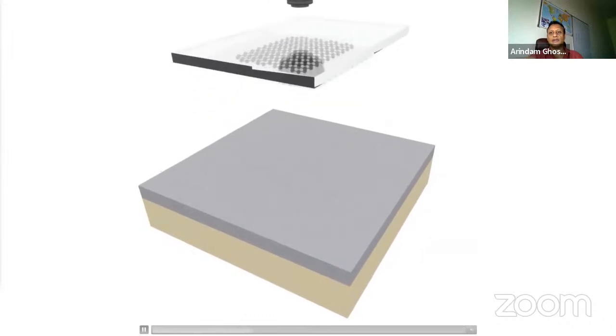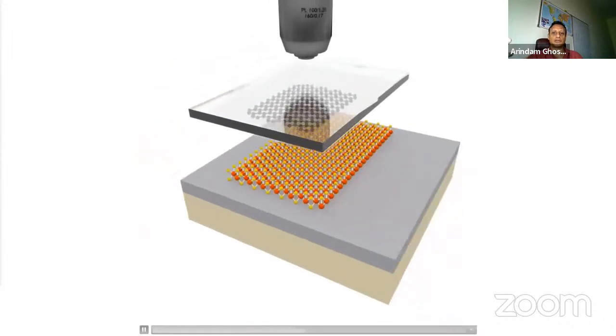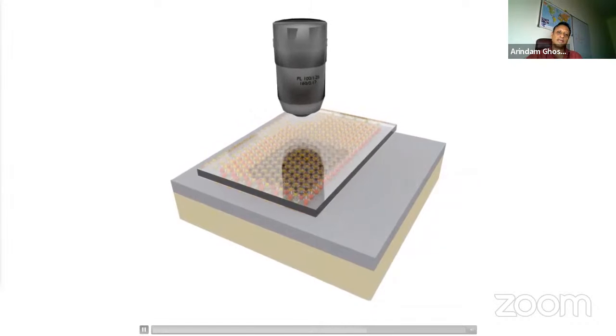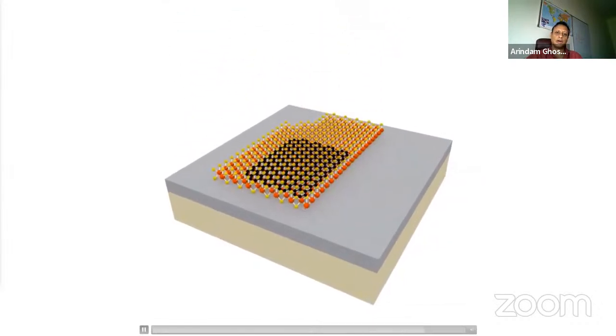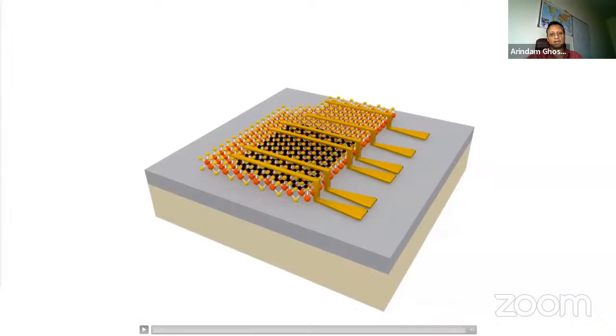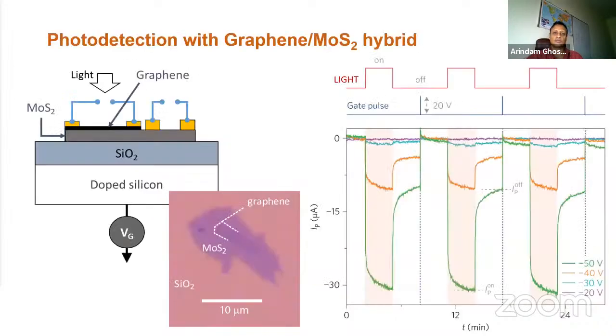That led to a new kind of optoelectronic transistor. What we did is we put the graphene on molybdenum disulfide and measured electrical conduction, something similar to this. What you see is something very interesting. Whenever you switch the light on this layer, the current through graphene, which is sitting on molybdenum disulfide, jumps dramatically by a very large number. And you can go on in cycles, and every time there is light, there is a change in current. And this current is called photocurrent.